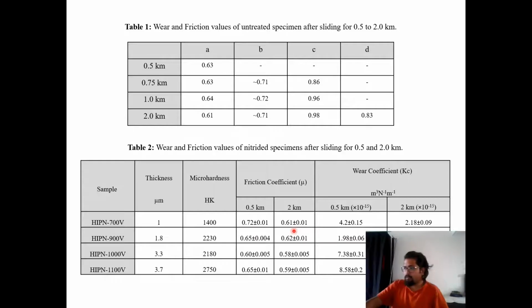But in case of 2 kilometer, because it's an average, we found that it's somewhere around 0.6, but in case of 1000 volt, the average was almost 0.58, which means with increase in bias voltage, the average friction value decreases.